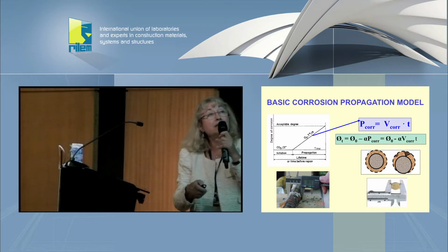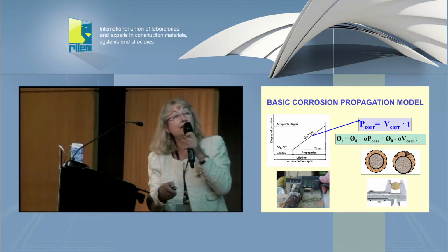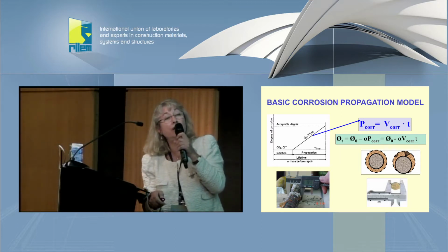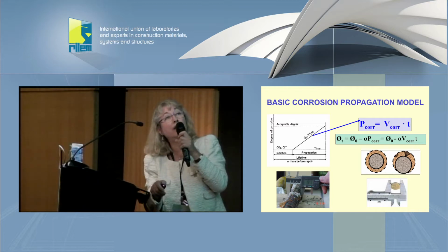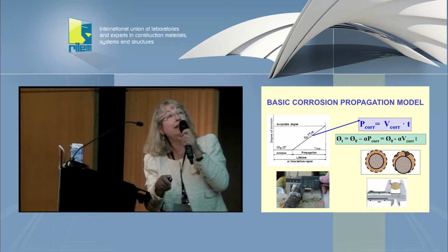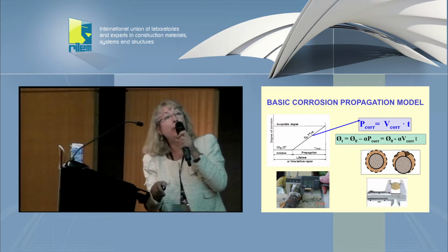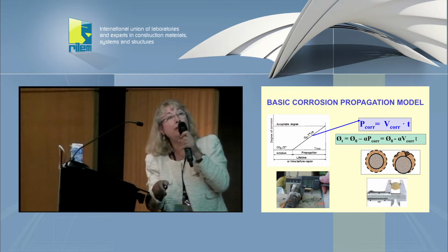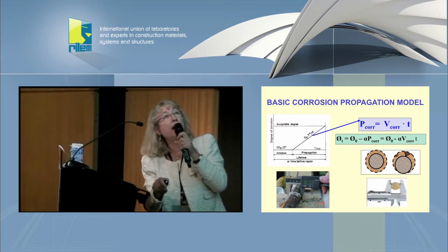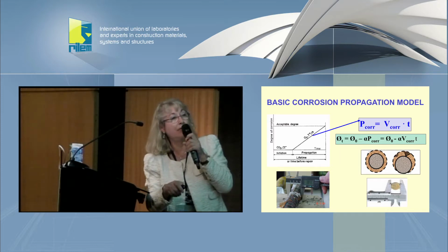And this is the most simple one, just measuring the decrease in the diameter. Also, it's possible to measure the pitting factor that we introduce as an alpha and apply to the diameter: the initial diameter minus the penetration at a certain age multiplied by the pitting factor, which we suggest as 10 times for the deepest pit, will give us the residual diameter after a certain time.